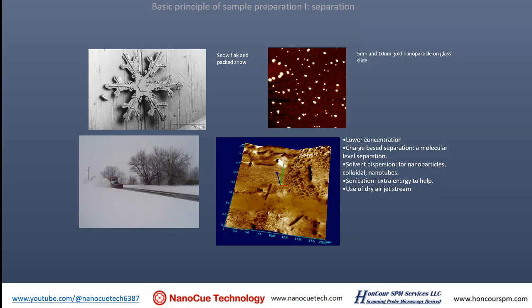Typically, to form a monolayer of any molecules on an AFM sample, it takes ppm or ppb. It's an extremely low concentration. If you wanted to see DNA, you have micrograms of DNA sample, and you have to dilute it 10 times, 100 times, many times, so you achieve a very low concentration. That's one way.